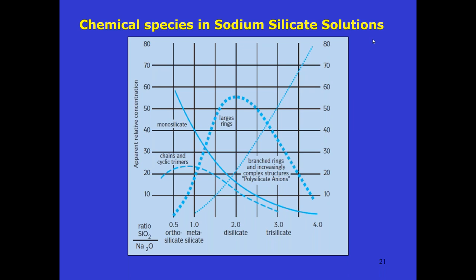You can see some names are put here, they are called dimers, trimers, because silicon will always be available in so many forms in our sodium silicate solution. Let me not go into too much detail on that. Silicon dioxide is present in the sodium silicate solution of the order of 30% or 25%. Whereas if you take silica alone, that is sand, and put it in water, the percentage which can dissolve is about 50 ppm of SiO2, which means 0.005%. Whereas we are having 30%, you can imagine how much silicon we have put into the water and we are not able to see it. That is the reason this silicon has entered into so many forms and is able to be inside the water.